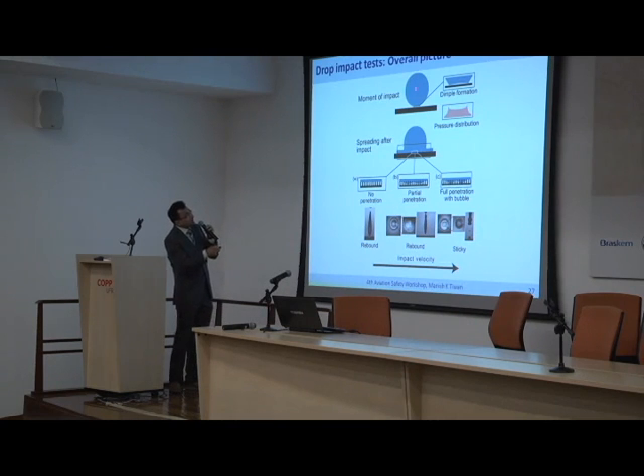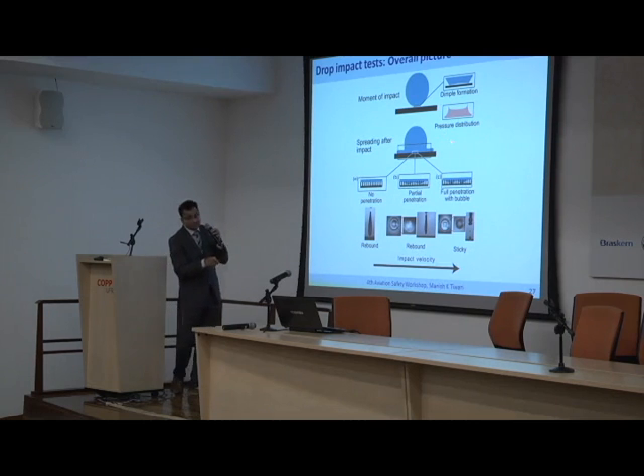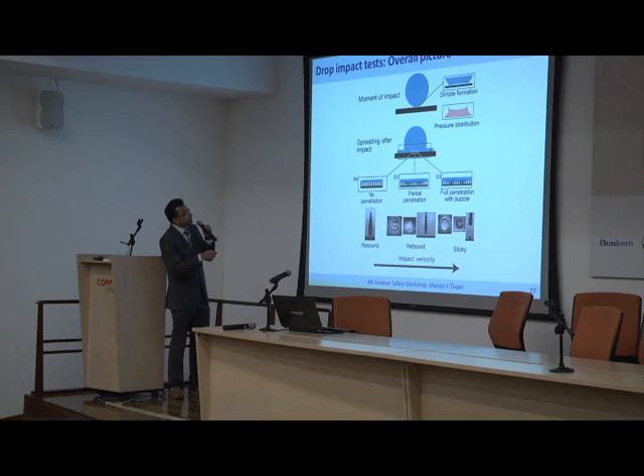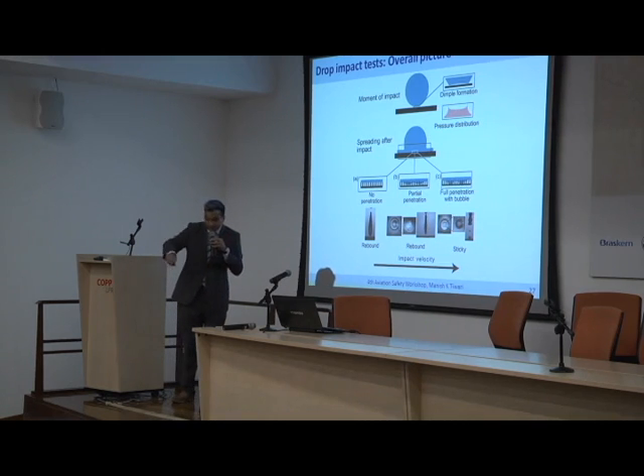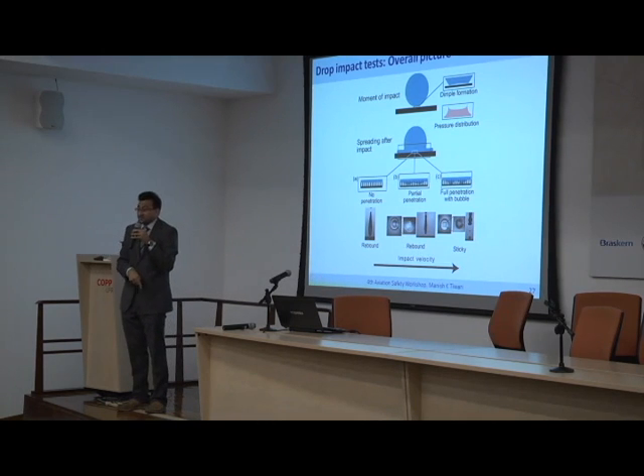What we have is basically a drop. This is also known theoretically, actually. And the pressure peak, the calculations show, I didn't have time to get into that, is a bifurcated peak. So you almost have a ring-like pressure peak, which is in agreement with the ring-like penetration that we are seeing from the top view.